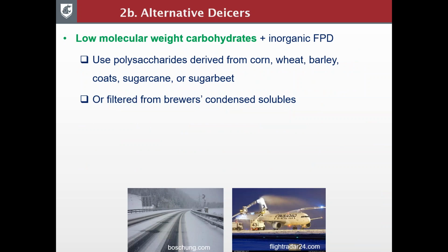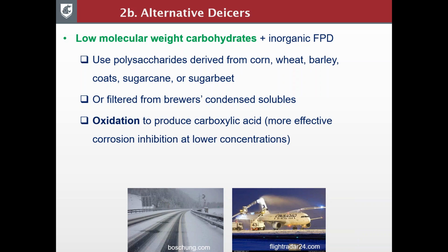Now, more recent advances are looking at degrading some of these organics to lower molecular weight carbohydrates and then blending them with some inorganic salts or freezing point depressants. For instance, some degradation is using the polysaccharides derived from corn, wheat, barley, or oats, sugarcane or sugar beet, or some filtering of the condensed solubles from breweries. Also, another group of technologies is looking at oxidation to produce carboxylic acids, which are stronger or more effective corrosion inhibitors at lower concentrations.